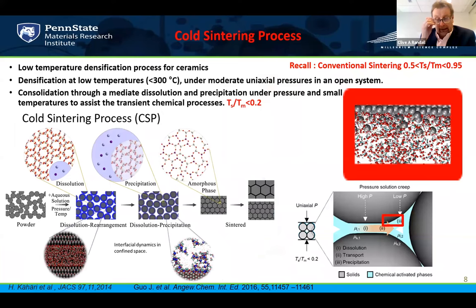So what is cold sintering? I think everybody that works in materials, particularly with particulate materials, knows the science of sintering. And there are many modifications to this, of course, with hot pressing and so forth. But just considering conventional sintering, the typical arbitrary material and what you would read in a textbook, the sintering temperature relative to the melting temperature of that material usually ranges between this broad range of 0.5 to 0.95.